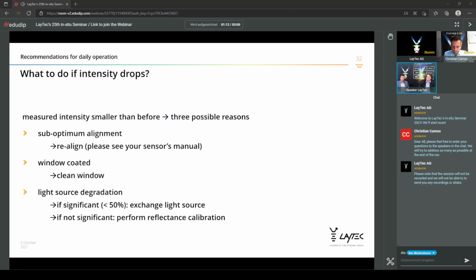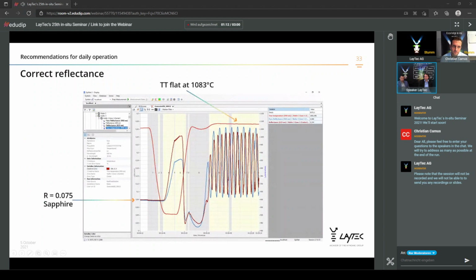As long as the light source degradation is not so significant, it's a slight decrease, this is normal lifetime, so over time the intensity will decrease. You need to perform the reflectance calibration. This will compensate for this effect. So, what does correct reflectance calibration mean? In that case, we show that for the sapphire wafer. On the substrate, we expect a reflectance of 7.5%.